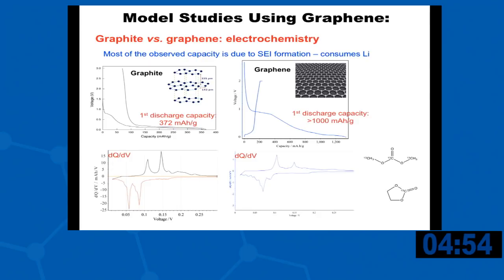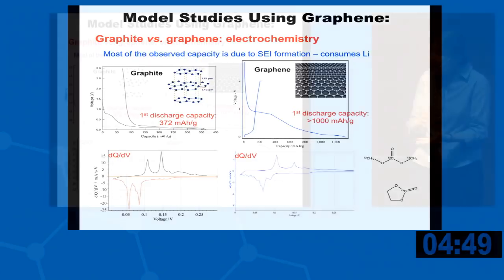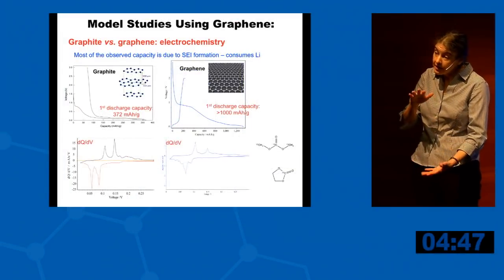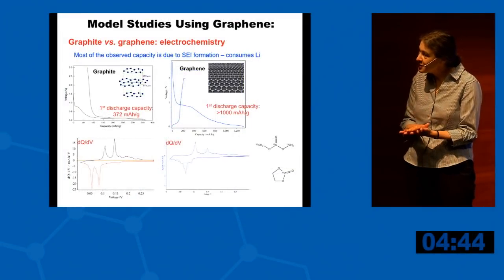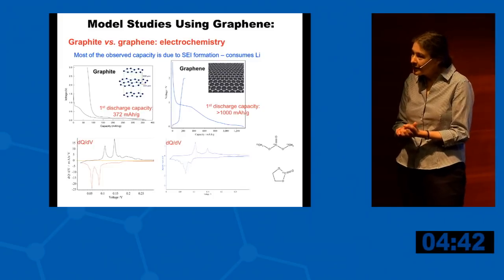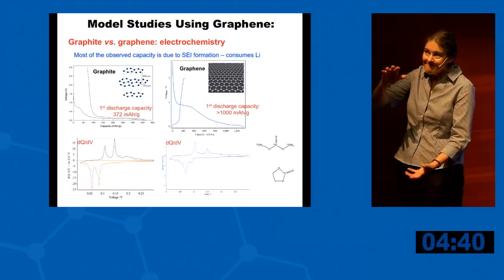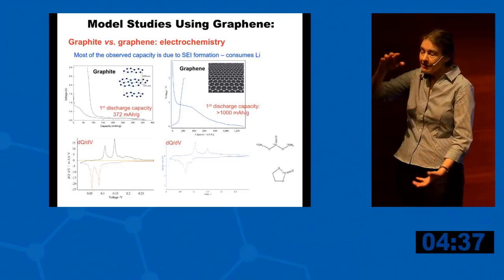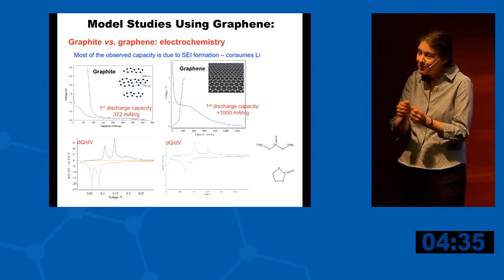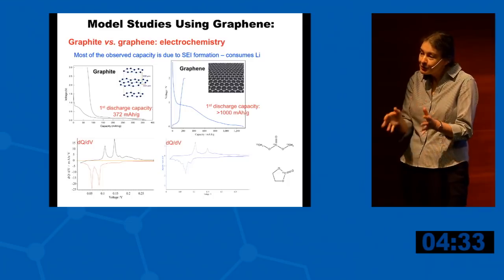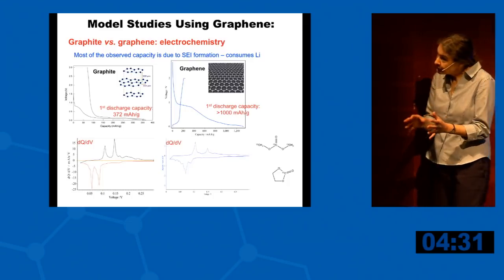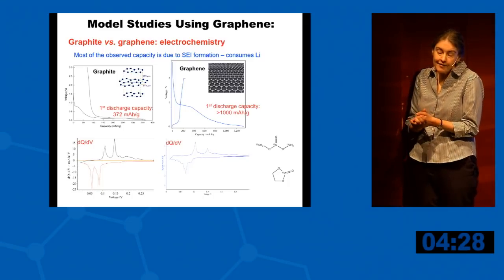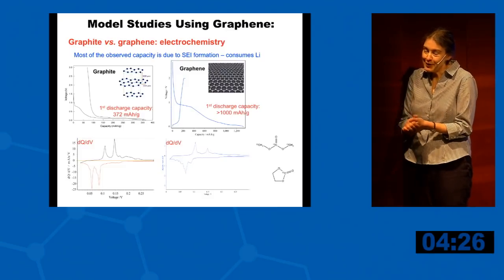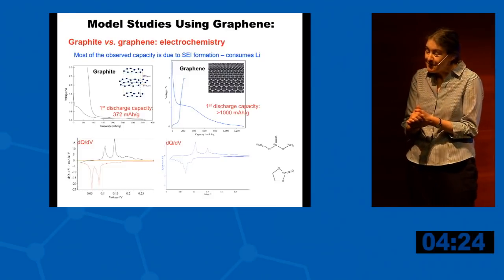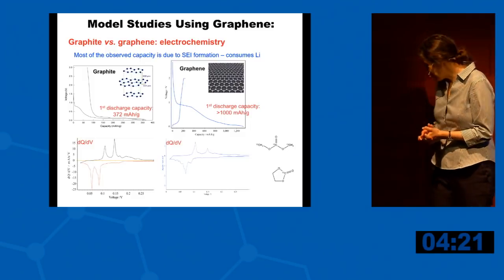But one thing that's sort of the bad news in the field is people are adding silicon with graphites, and these expansions of the silicons are actually grinding the graphites. So that's going to be another problem we're going to have to address, because this particle is not as soft as I used to think it was. It's expanding threefold, and it's pushing all the carbons nearby. So it's a real challenge to solve those problems. I don't have the answers to that one, I must admit. I've been trying to work on this for 10 years now. But I have clues, not answers.